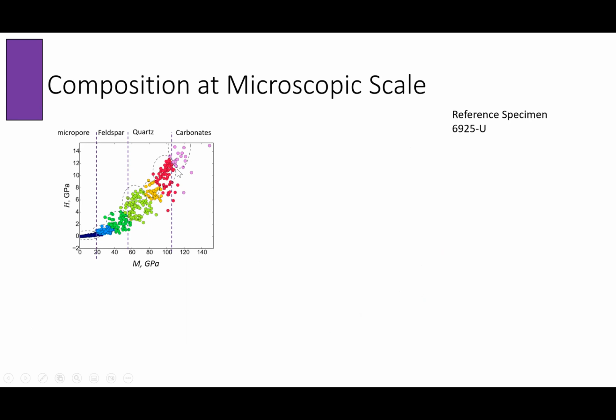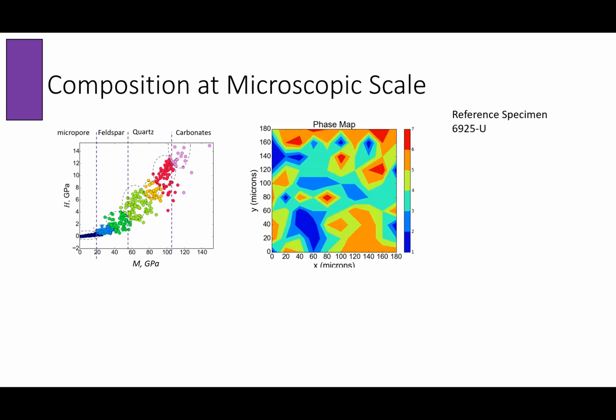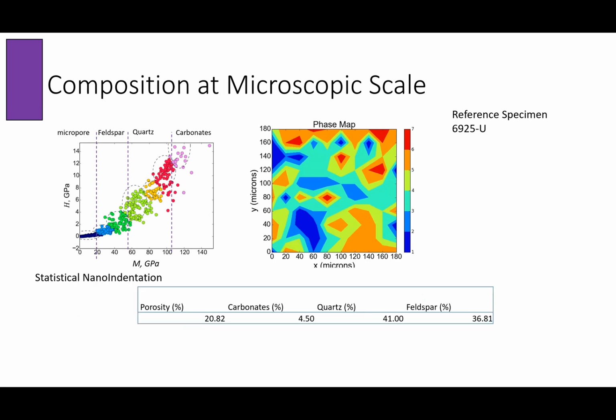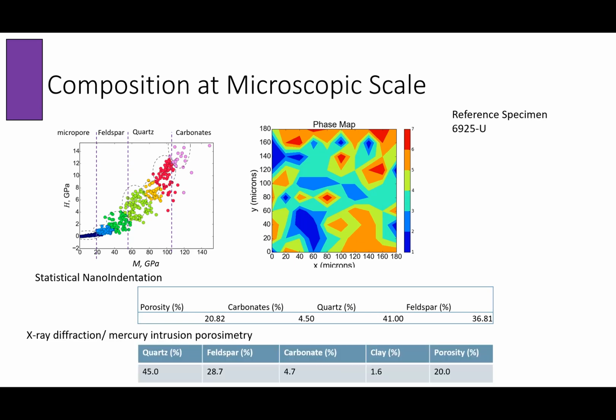And these are the same ones that we observe using SEM and SEM EDS, but this time using nanoindentation and grid and statistical deconvolution, we are able to visualize them, create a map of the different phases, and we can quantify them. We can quantify the porosity and the fraction of carbonates, quartz, and feldspar, and we can show that we have an agreement with, on the one hand, mercury intrusion porosimetry, but also on the other hand, quantitative analysis using X-ray diffraction.